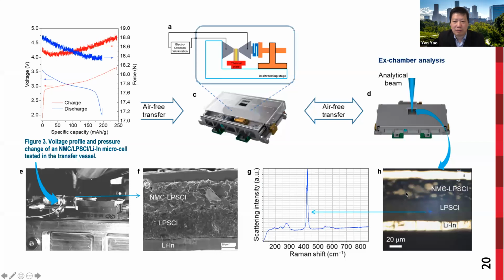So the test platform has also been optimized to deliver performance similar to non-micro cells. The first discharge capacity reached 200 milliamp-hours per gram, which is comparable to thin cells. The pressure change can also be monitored in situ. So these results indicate the efficacy of the vessel in isolating the test platform from ambient conditions without interfering with any analytical beams.